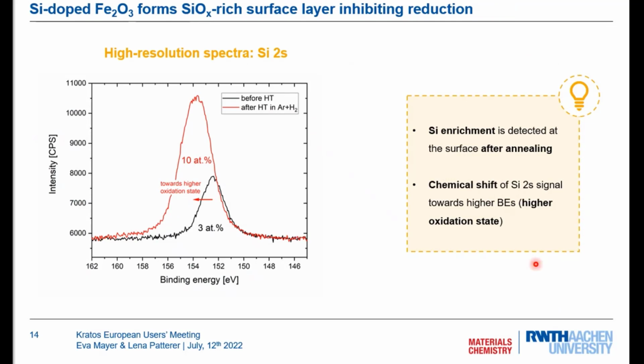And now for the silicon. We also had a closer look at the silicon 2s signal. So the silicon 2p was unfortunately overlapping with the iron signal. But when we look at the silicon 2s signal, we can definitely see that there are some changes happening. So in black, we see before the heat treatment in the hydrogen atmosphere, and in red, we can see the signal afterwards. And from the survey spectra, we definitely see an increase in the silicon concentration.